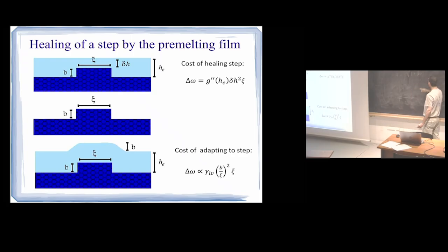This will be a measure of the increase in slope integrated over the full range, where the slope is finite. Now you equate these two results, and you find that the surface will be healed only if the length of the imperfection is given by this distance. That's the surface tension over the second derivative of the interface potential.